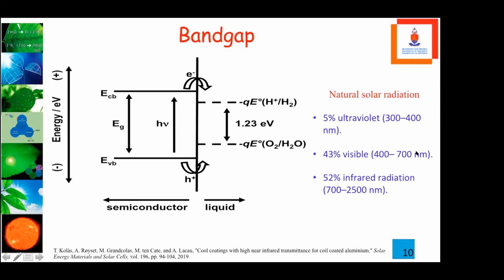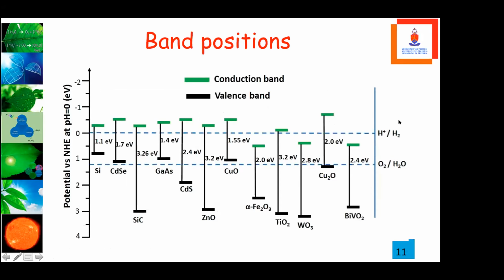When we look at the band gap, you find that natural solar radiation consists of 5% ultraviolet light. So it becomes difficult for you to use a material with a bigger band gap, a band gap that absorbs in the ultraviolet light. 43% is in the visible, which takes most of this, and that's what we need, and 52% in infrared radiation. So these are the band positions. That's your conduction band, and that's your valence band. This is your hydrogen production position, and that's your oxygen production position. You must be able to find a material amongst all of these materials that you see here. People have used them and they are published.